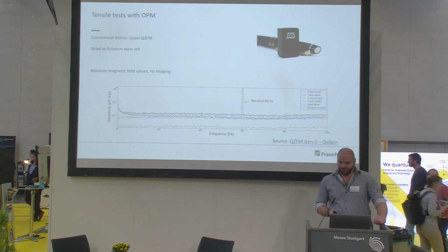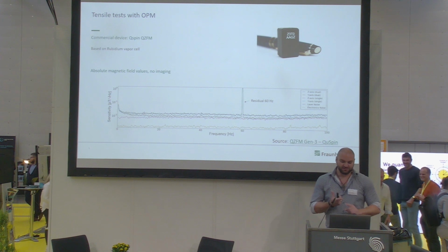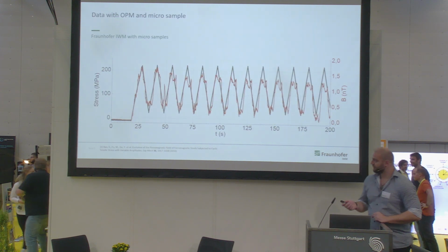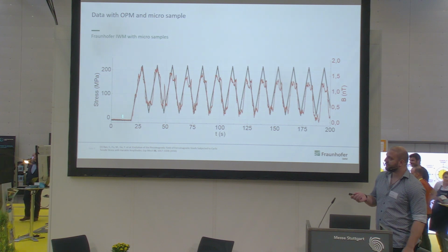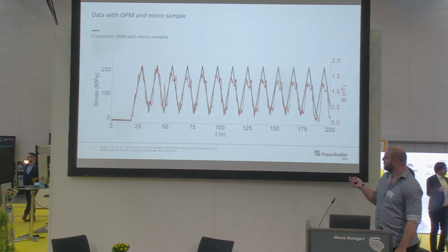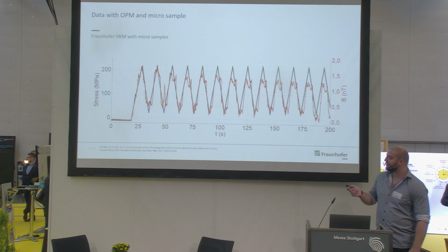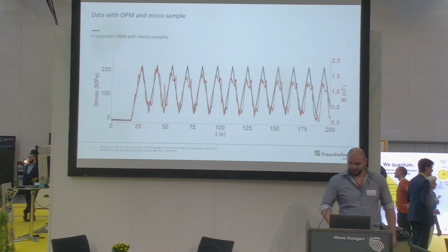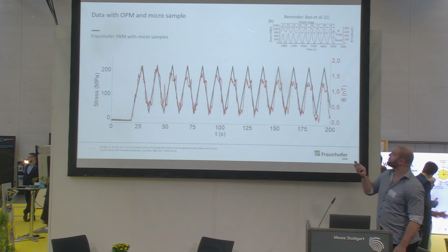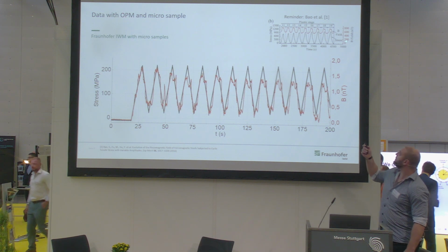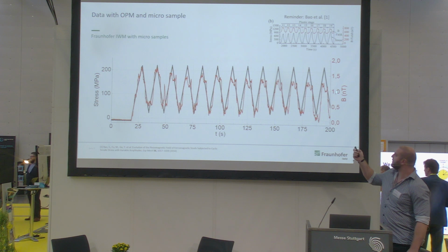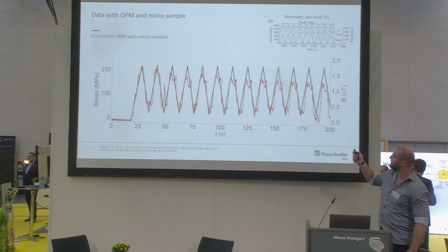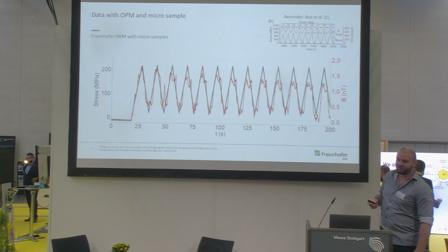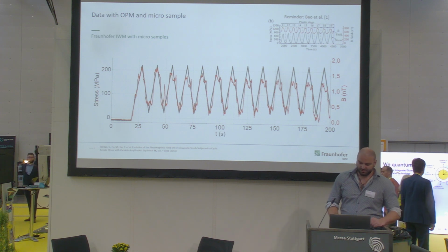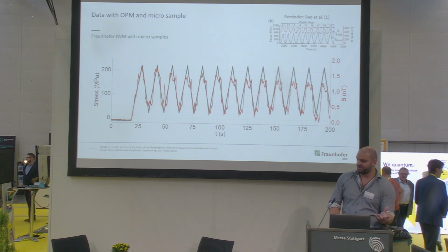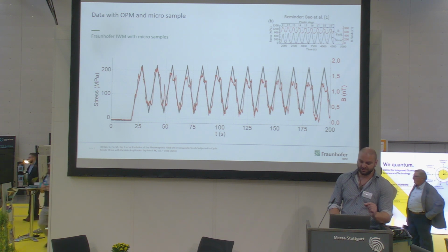So now we have the microsamples, we have the super sensitive sensors. What do we see if you use these things together? This is data from our institute. We have in black again the stress as a function of time, and you have in red the magnetic field as a function of time. We can see the magnetic field follows the curve. As a reminder, that's what Bao et al. see in the literature at huge samples. And if you look at the magnetic field scale, we go here up to 800 nanotesla, and we are a factor of like, what is that, 400 smaller? And we can still see it, it's 1 to 2 nanotesla actually. So we can reproduce the state of the art on macroscopic samples with our microsamples and these OPM sensors.